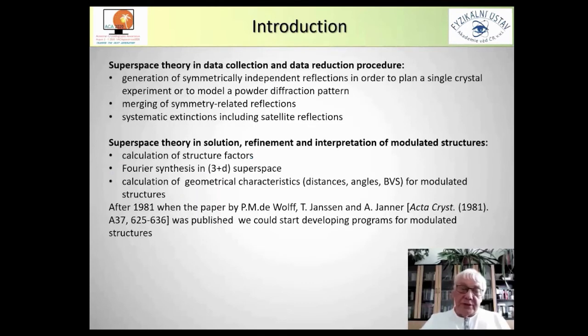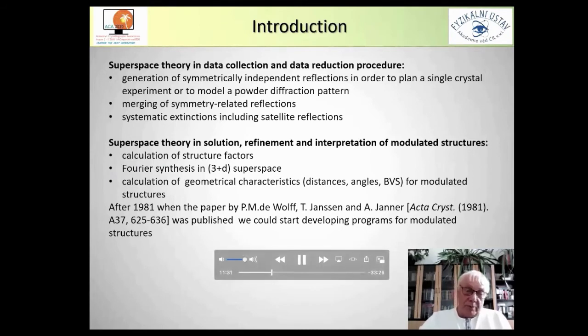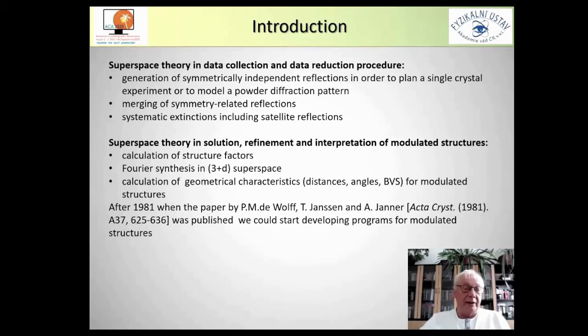The superspace theory can be used in data collection and in data reduction procedure. You can use this theory to generate symmetrically independent reflections in order to plan a single crystal experiment or to model a powder diffraction pattern. For merging symmetry, we can also use superspace theory, and moreover, we can simply derive systematic extinctions, which include also satellite reflections.